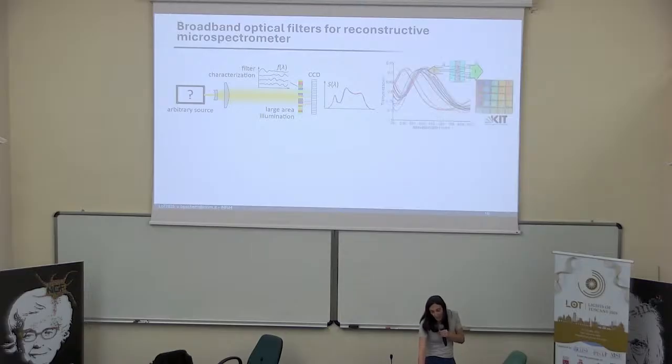We have really no idea about the smooth transfer function of a dielectric filter, and when I talk about a dielectric filter, think of a few layers of polymeric material with alternating refractive index. A few layers, two to three layers. With these two to three layers we can cover 300 nanometer bandwidth. So look at these transfer functions. They are really smooth.